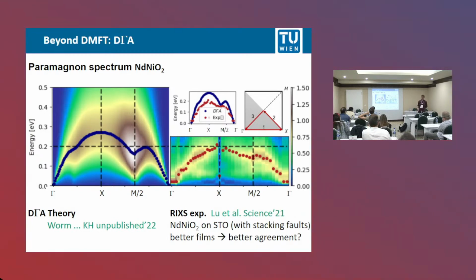So if you have disorder, our understanding from doing a lot of calculations, which I'm not having time today to show, with excess hydrogen, is that then you have also at least locally some ferromagnetic exchange, some disorder in the exchange, and then you should expect such a difference here. And we would now predict that the cleaner films will then end up somewhere in between our theory and the old experiment. Okay, so that gives overall a nice agreement.